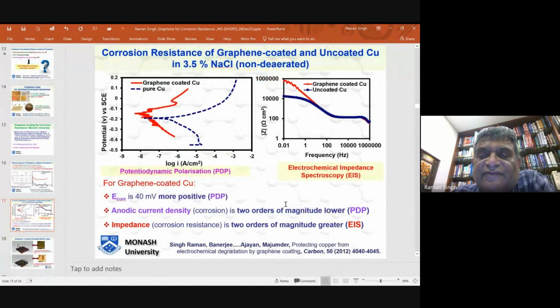So we got these graphene coated copper and pure copper samples from Ajay's group. We did typical corrosion tests, which are the polarization test and electrochemical impedance spectroscopy, similar to the plots that I showed you earlier. You can see that the intercept of these two once again gives me corrosion resistance. What I'm trying to show you here is the intercept for the graphene coated sample and the pure copper sample. If you compare, the graphene coated one has 100 times smaller current. The lower the current, the better the corrosion resistance. So just one atomic layer thick graphene improved the corrosion resistance of pure copper by 100 times. Just one single layer, right?